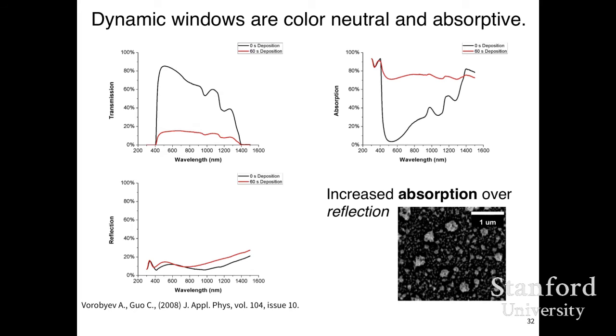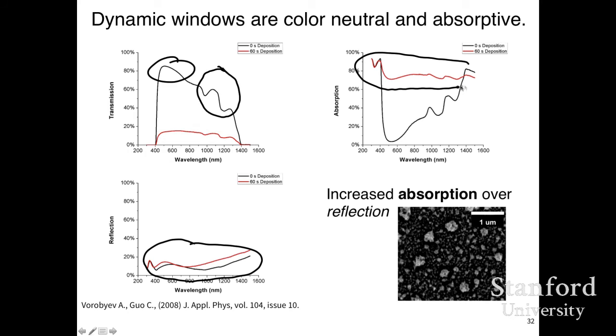This slide takes a more detailed look at some of the optics. You can see the transmission in the clear and the dark state, and in the clear state, it is clear in the visible, but the ITO is absorbing out in the infrared. And then we see that there's not a whole lot of reflection off of the device, maybe 10 to 20%. Most of the impact of plating metal is in the absorption, and we see here we're getting about 80% absorption across most of the film. And I don't think we understand that in full detail yet.